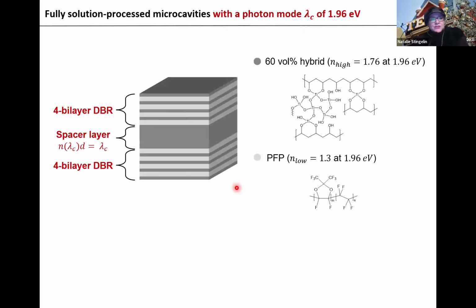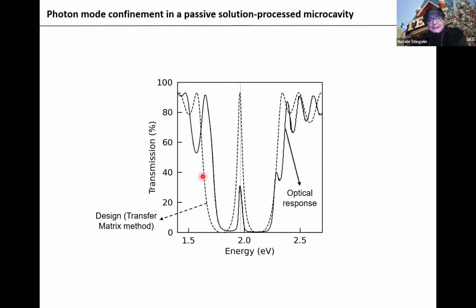You see now, in solid line is the measurement. When we have this structure with this spacer layer, this defect layer in there, we don't have a mirror, but we have a mirror where at very specific energies or wavelengths it opens up. And again, we have pretty good agreement with theory - these are the dotted lines.